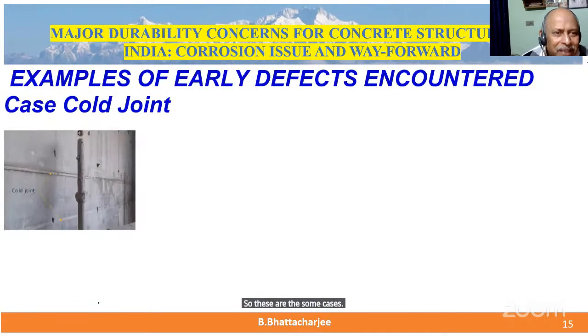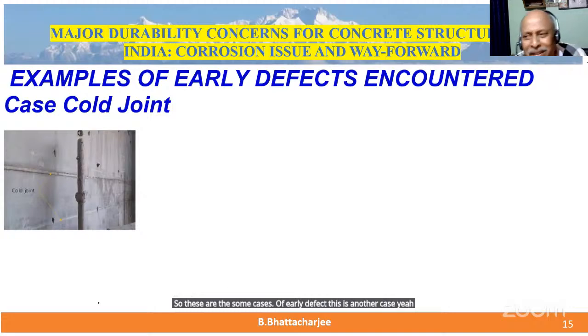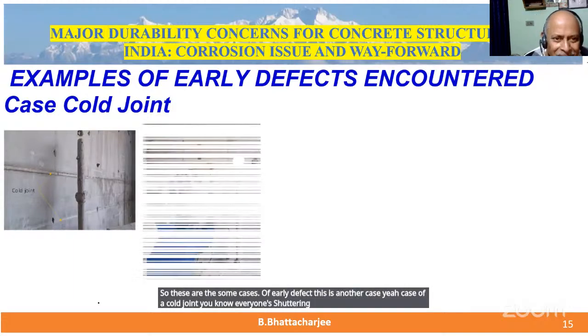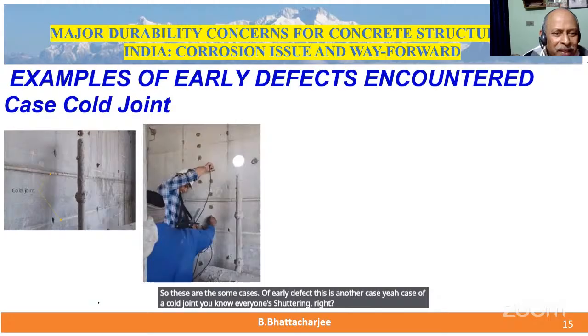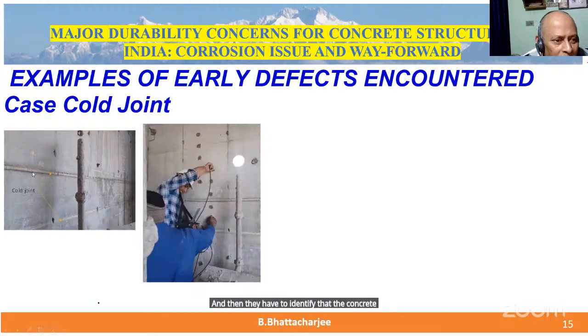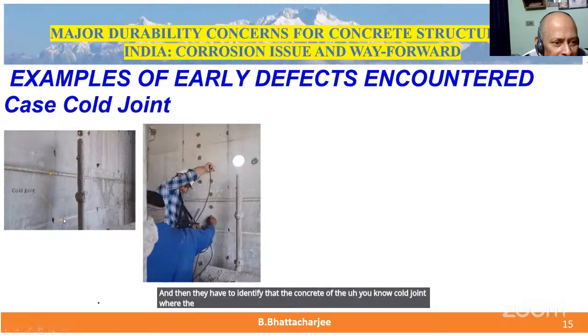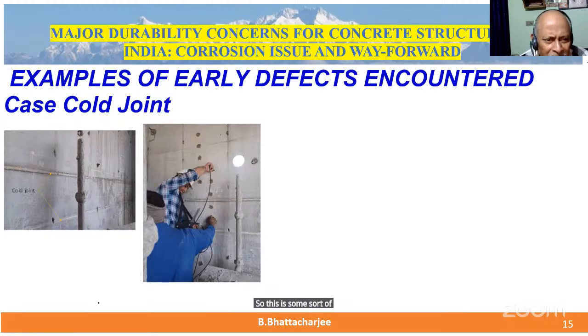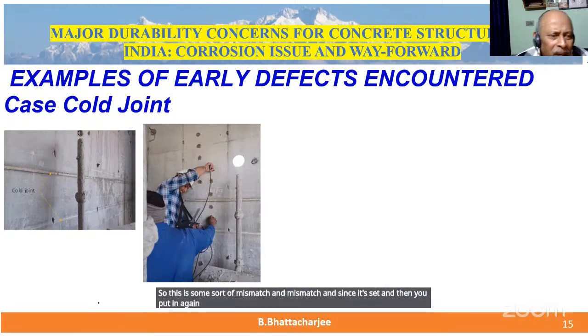of early defect. This is another case, a case of a cold joint in Mivan shuttering, right? And then I had to identify where the cold joint is there, here, because again, they delayed the lifting of the form wall. Mivan shuttering is everything together. So there's some sort of mismatch. And since it's set and then you poured in concrete, cold joint formation occurred. One has to prove that this has happened.